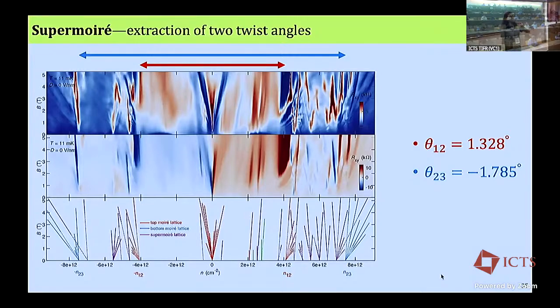All I can tell you is that in our lab, we cool down the same sample multiple times and we end up seeing the same thing. So maybe I'm not cold enough. Our coldest fridge can go to, we say 12 millikelvin because that's what the fridge shows, but my anti-dot measurement tells me it's 100 or 120 millikelvin. We measure some dots also, gallium arsenide and graphene, so we know the temperature. Other people may have lower temperatures.